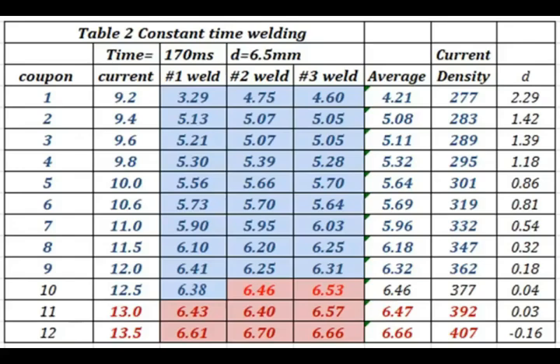I converted the current to current density so this table can be used for a weld cap that has a different diameter. The first acceptable weld occurs at 283 amperes per square millimeter and the first expulsion weld occurs at 377 amperes per square millimeter. The midway point is 330 amperes per square millimeter. If you weld between 300 to 330 amperes per square millimeter, you will always weld a good quality weld without expulsion.